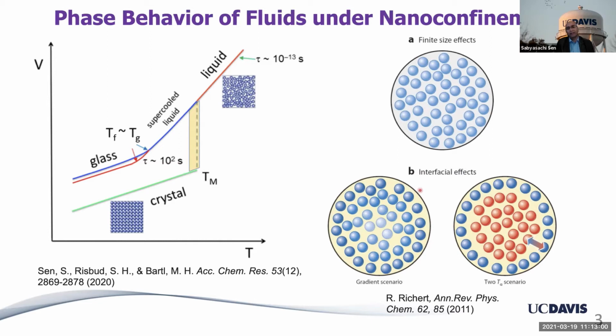On the other hand, you can have also interfacial effects between the confining medium surface and the liquid surface. So at this interface, the structure of the liquid could be different compared to that in the interior, and the structure could gradually change, or there could be a core shell type structure with a two liquid type scenario. So these are some of the possibilities, and these are controlled by the interfacial effects.